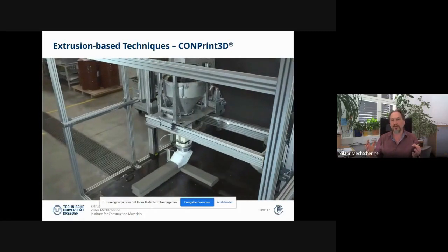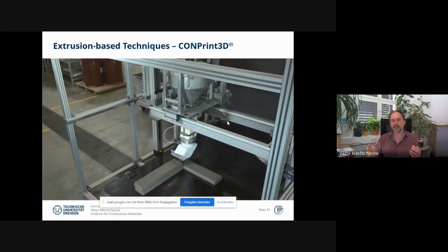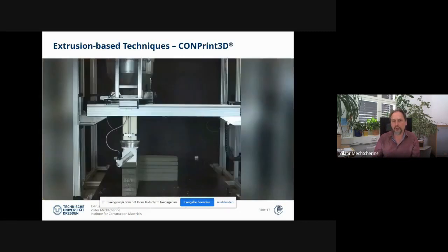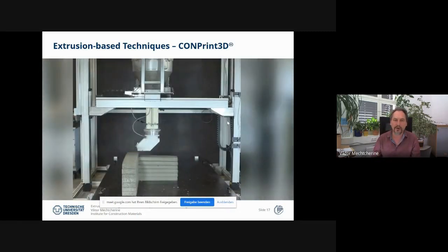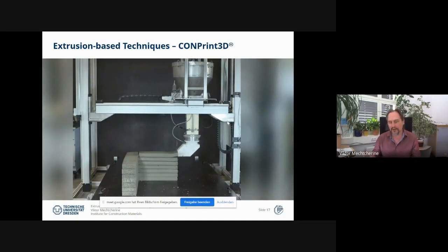We have the possibility to print concrete layers with a width of 15 centimeters and a height of 5 centimeters. In this particular example, we use concrete with a maximum aggregate size of 8 millimeters, and it's close to the framework which we get from the codes. So this is an example of how such printed elements look.